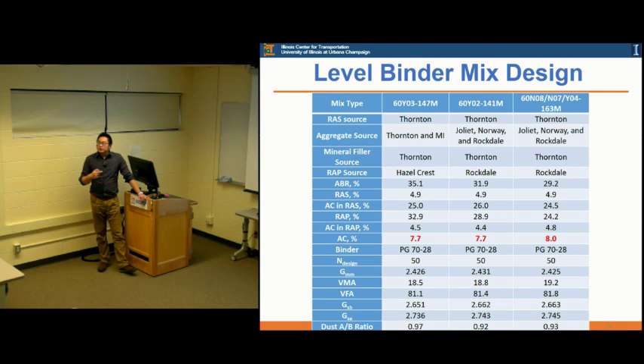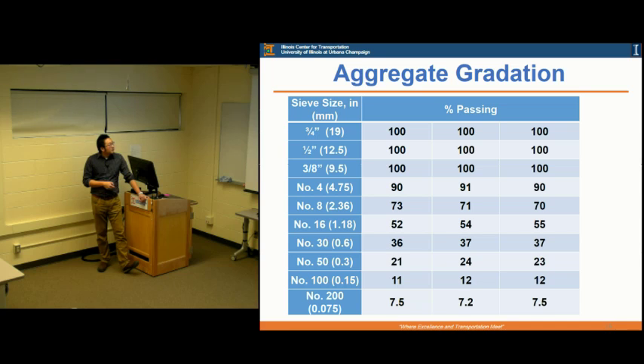But now we are using that level binder course. This is the mix design for actually 5 contracts. Y03, Y02, and this is 3 contracts use the same mix design. You can see that they are pretty much very similar in the mix design, but the only thing you can see different is the AC content a little bit. For the 163, you have 8% asphalt content, but the other is 7.7. The other difference is very minor. As you can see, RAP and RAS, of course you end up with a different ABR content. Other than that, even for the aggregate gradation, you can see they're very close.